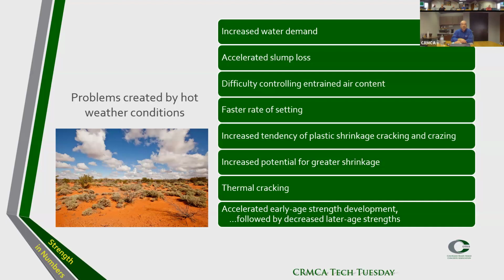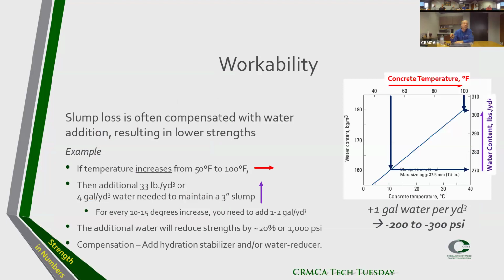Plastic shrinkage, cracking, and crazing are increased generally if you have hot weather conditions. You have more potential for shrinkage. Thermal cracking might be an issue. And what we see quite often is that you have pretty nice early strength in the concrete, but later you will see that the 28 days don't make it that high. So it accelerates in the beginning, but it tapers off really fast if you have hot weather, hot concrete.